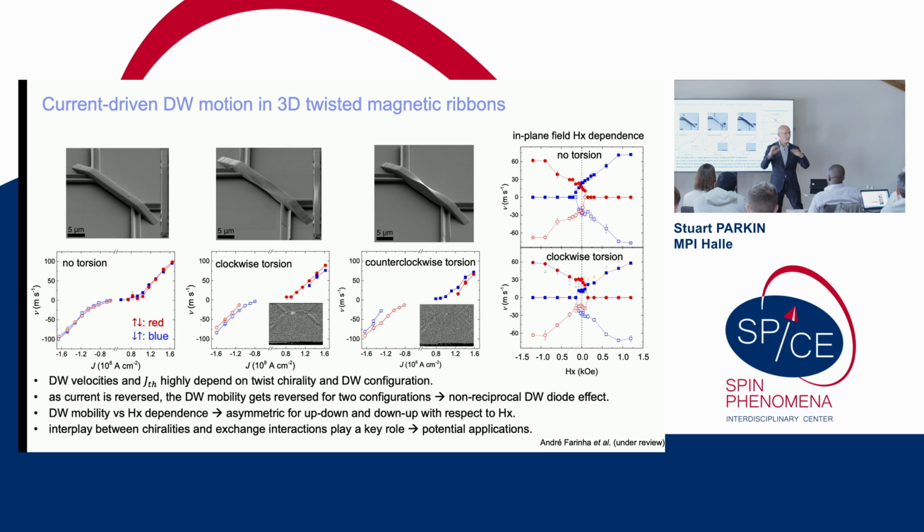So you can see, it's like a diode. It's because we've created, through this torsion, an additional curvature. Curvature creates a new DMI exchange, which competes or adds to the DMI exchange innate to the structure itself. So we can have a competition between the geometrical and spin chirality in this way. We think this is very interesting. This is the second three-dimensional racetrack.